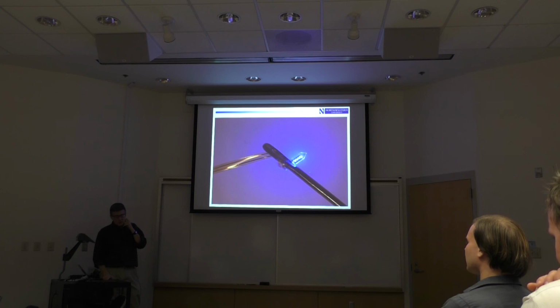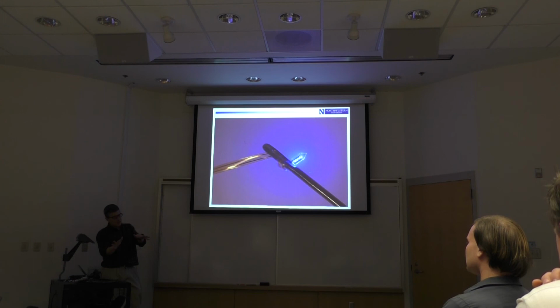What we ended up settling on is basically we take a silicon wafer, it's a spectacularly sophisticated piece of materials technology, very, very flat surface, structurally perfect in terms of single crystal. Then you can grow a thin layer of glass on top of it. So you're exposing the oxygen, reacting with the exposed silicon, and you can grow thin films of SiO2. And then you get rid of the substrate, you have a very, very perfect thin layer of glass, and you can basically cap your device with that.